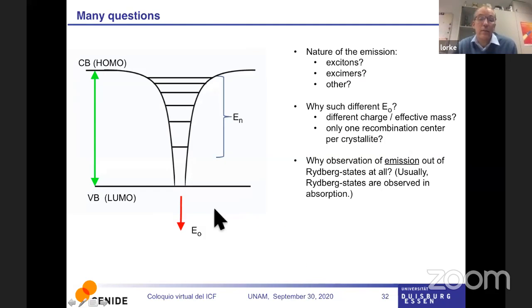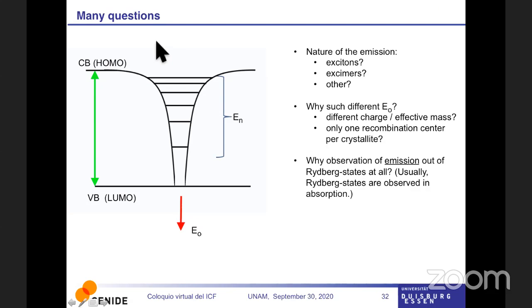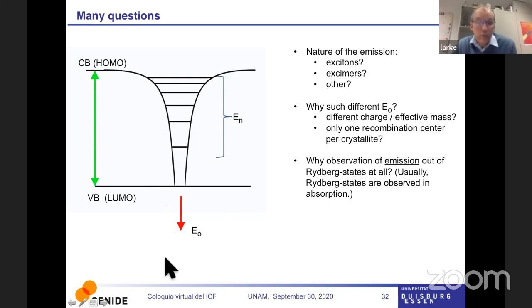There is another puzzle. The other puzzle is, where is E1, or E0 for n equals 1? It is sometimes extremely low in energy, lower in energy extrapolated, if you extrapolate to n equals 1, lower than the band gap. And how is that possible? How can something sit all the way down there? And why do we see these Rydberg states at all?